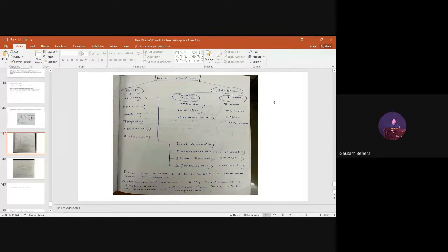So the entire bulk of the steel will be at the transformation temperature. But what is surface heat treatment? Surface heat treatment is only the surface, not the inside or the core. Only the case or the surface will be at transformation temperature. That's why it is called surface heat treatment. It may be 1 mm or 2 mm from the surface, but the entire bulk will not be at the austenitizing, soaking or transformation temperature. That is the difference between bulk and surface heat treatment.